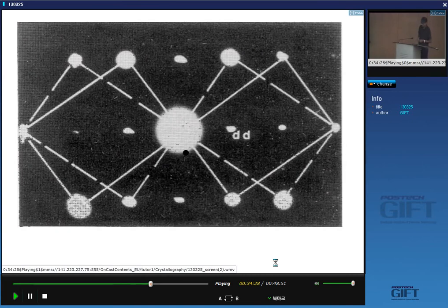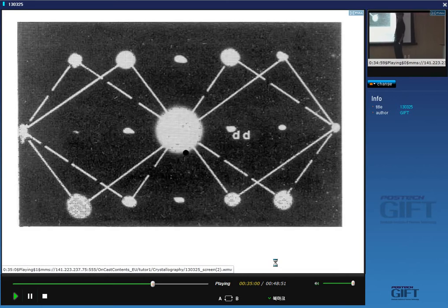Here's a diffraction pattern of those two crystals, Z and X. Here is one zone, and this is another zone from the second crystal. And this is a 110 type diffraction pattern from both crystals. But obviously, the patterns are rotated. Now you can clearly see what the rotation is. If I take this axis here and rotate by 180 degrees, I generate the other crystal, right?